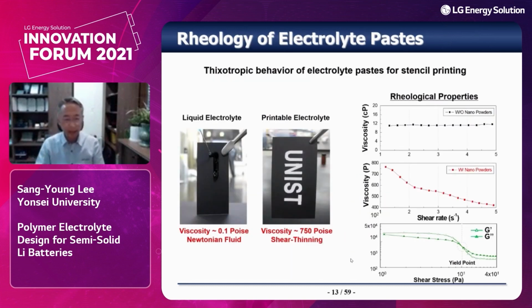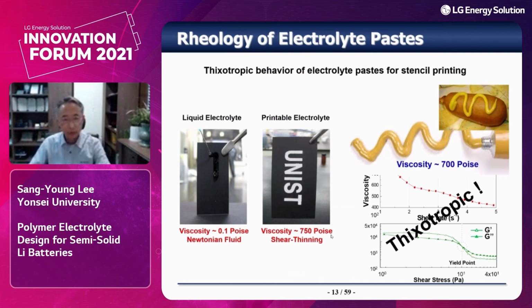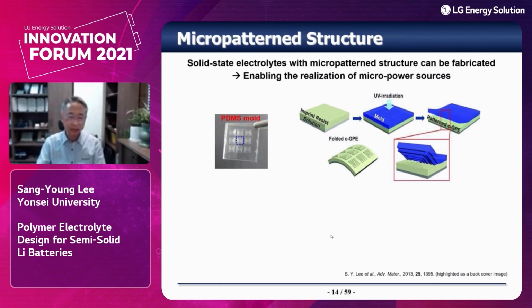Anyway, the underlying technology enabling this achievement is as follows. The liquid electrolyte has low viscosity and shows Newtonian fluid behavior. By comparison, our electrolyte shows shear thinning behavior. More importantly, if you look at the viscoelastic properties, at a certain point of shear stress, G prime and G double prime cross over, which shows the typical thixotropic fluid behavior. By exploiting this unique behavior, we have successfully fabricated the printable electrolyte. Please bear in mind the viscosity value, 750 poise, which is similar to that of mustard. So our electrolyte paste seems to be similar to toothpaste.